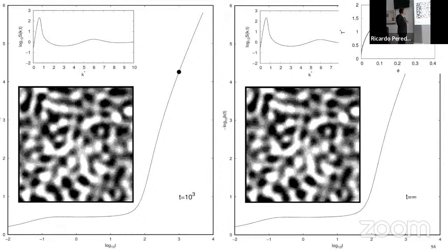So such a spinodal decomposition process ends up stopping just because of the mobility of the system. This is the inverse of the mobility. So if the inverse of the mobility increases, the mobility decreases. When approaching the dynamically arrested states, such an increase in the inverse of the mobility just displays that the system stops diffusing. The diffusion is very, very low.